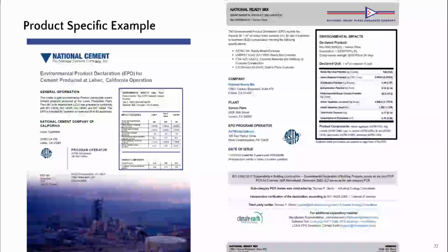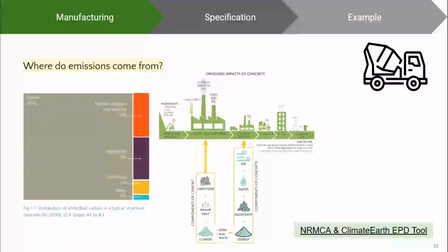With the cement providing the highest contribution of global warming potential to a concrete mixture, that's an important aspect to look at. A bulk of the emissions come from that pyro process where we take the limestone and fire it in a kiln. So we have to have lots of energy to process that limestone to reach those high temperatures, and then there's the chemical reaction that takes place in the limestone, where the CO2 is emitted. So that's a bulk of the emissions produced in the cement making process, and that trickles down to a bulk of the emissions in the concrete.